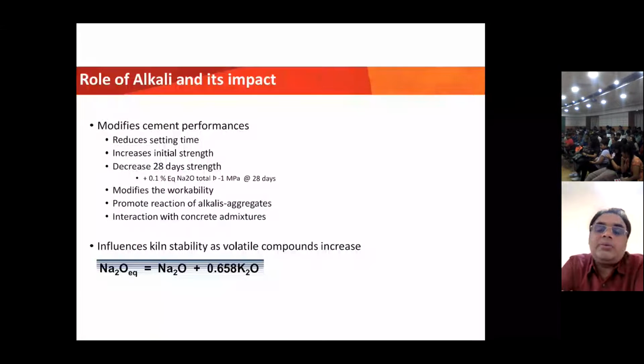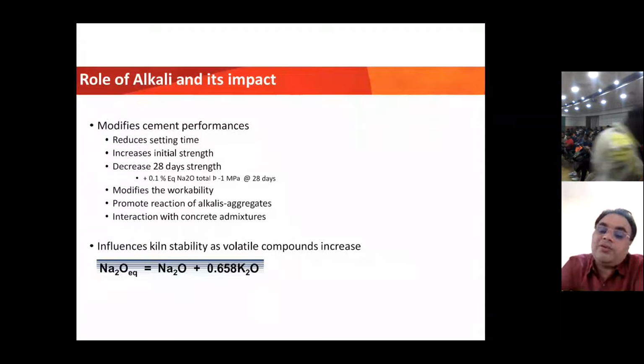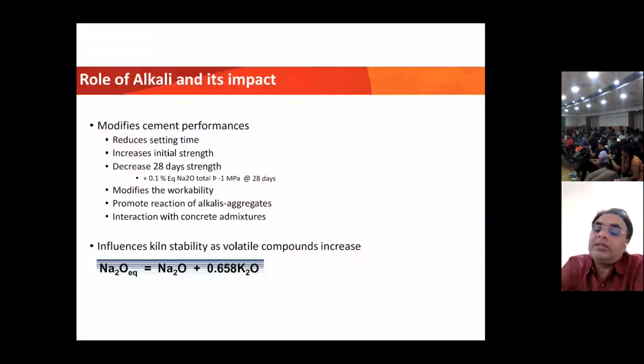Alkali, as concrete students and concrete engineers know, is a very important parameter, because you will be adding different aggregates with the cement, and you will be adding some admixtures to control the setting time and the workability, which in a cement plant we call the normal consistency or the water demand. So this is very important. Alkali is one of the factors which really impacts all those parameters in the concrete, right? Because of the alkali silica reactions from the aggregates, and the alkali, whether it is coming from the cement or from the aggregate, whatever you are using, you have to ensure that it matches so that you can have a better concrete quality. So it modifies the workability and promotes the alkali aggregate interaction with the concrete admixture.